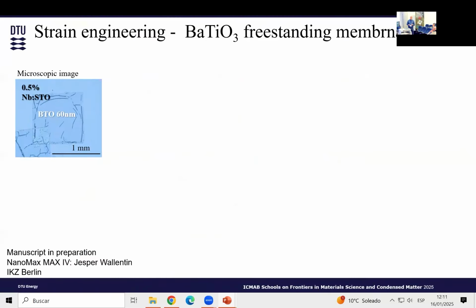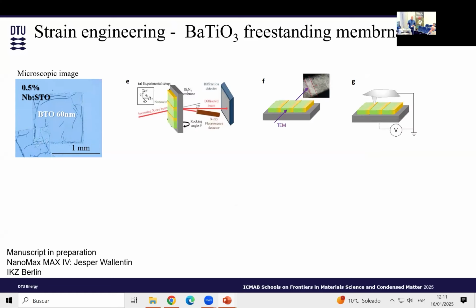Okay, and this is another way about the strain that we looked at in the barium titanate. So what we did is we did like any other people do. We grow the barium titanate, we release it, we transfer it, we put it onto niobium-doped strontium titanate, and then we took it to the beamline in Lund, in the MAX IV. It's a nano beamline, and we investigated the material. I will come in a second to what we have seen. We also did TEM, and we did PFM on the material.